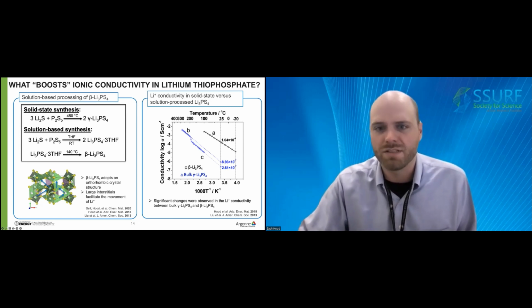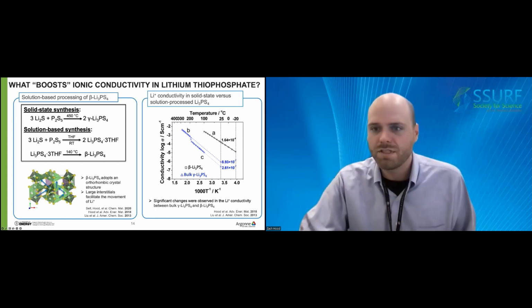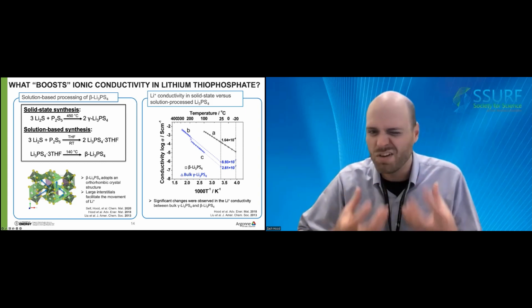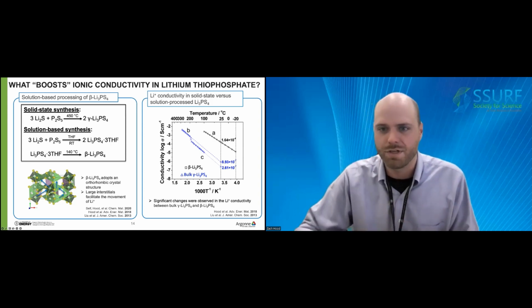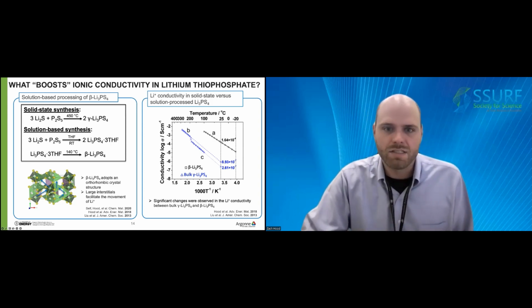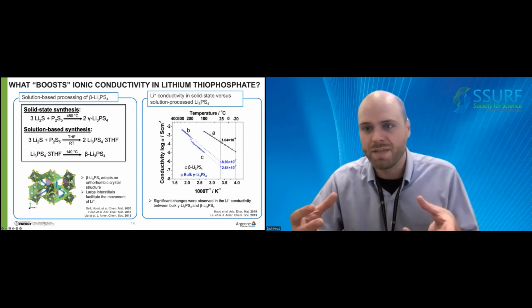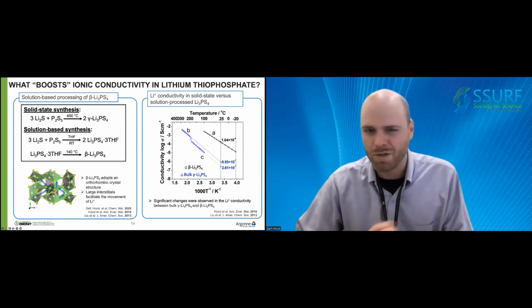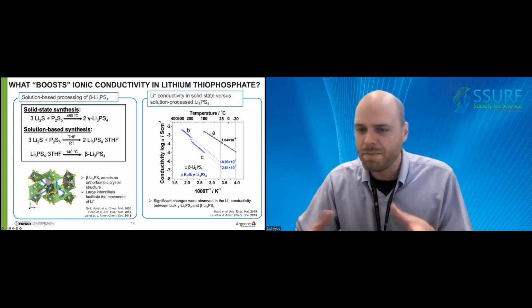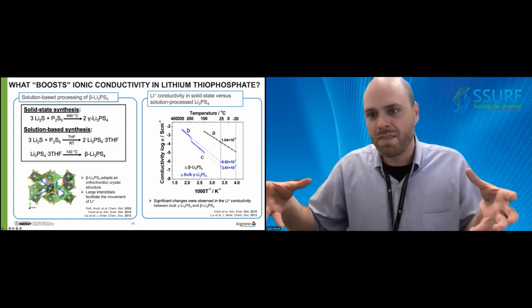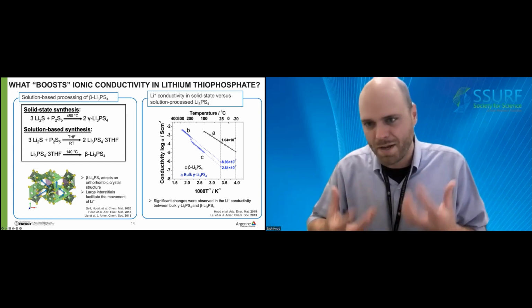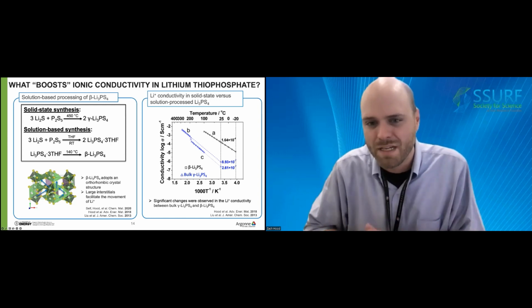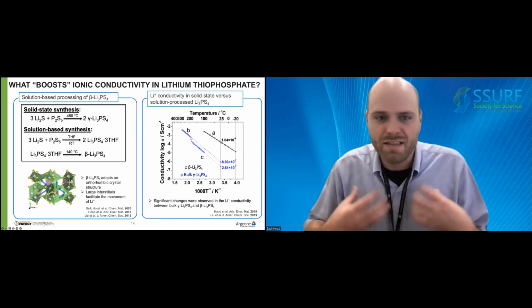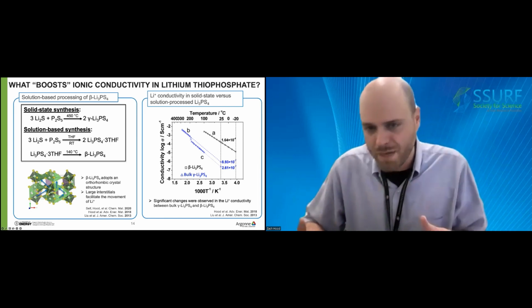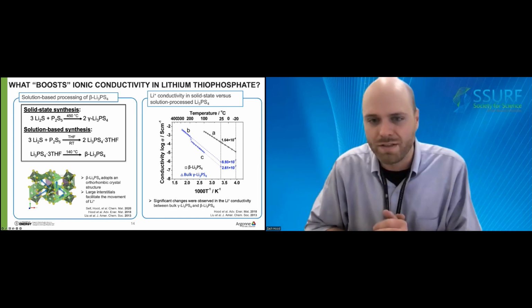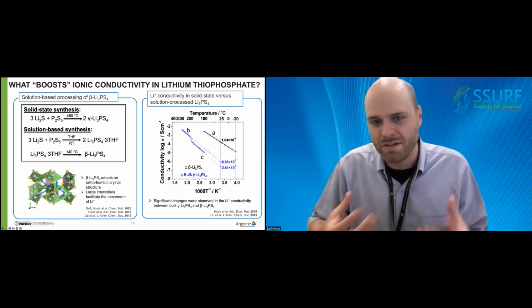Within the sulfide-based solid-state electrolyte system, we were interested in exploring solid electrolytes that utilize low-cost materials such as sulfur and phosphorus. Classically, solid-state methods were explored to synthesize lithium thiophosphates using evacuated Pyrex or quartz ampules. And this results in the gamma phase of these lithium thiophosphate-based solid-state electrolytes. And at Oak Ridge National Lab, we demonstrated that we can synthesize lithium thiophosphates using innovative solution-based processing techniques using polar solvents, such as acetonitrile and tetrahydrofuran.